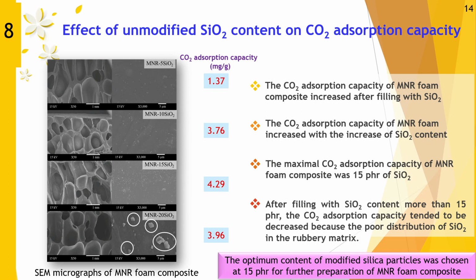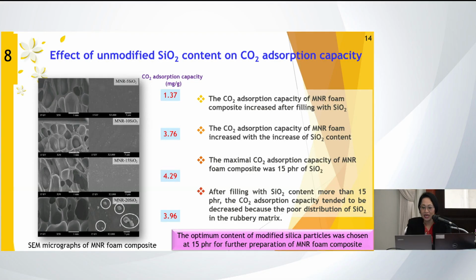After filling with the silica content of more than 15 phr, the carbon dioxide adsorption capacity tends to decrease because of the poor dispersion of silica particles in the rubbery matrix. Accordingly, the optimum content of the modified silica particle in this study was chosen at 15 phr for further preparation of the modified natural rubber foam composite.